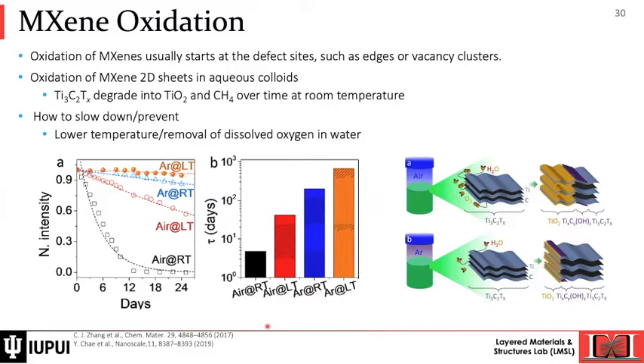This is coming from the first study, basically showing that if you want to slow down or prevent MXene oxidation in colloidal solution, you can lower the temperature, meaning put it in the fridge at 5 degrees Celsius, or you can also remove the dissolved oxygen in water, meaning that if you just argon bubble this solution to remove any dissolved oxygen, you can enhance the stability of MXene. Up to 2 weeks, you will see that there is really no degradation when we have this solution of MXene under argon at low temperature, and low temperature is 5 degrees Celsius here. And you see that there is almost no oxidation, or very little amount, when we keep it in argon.